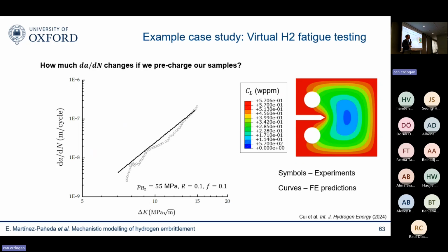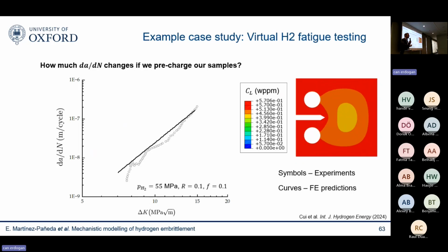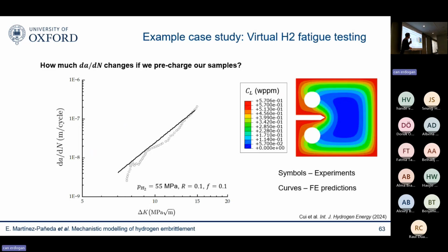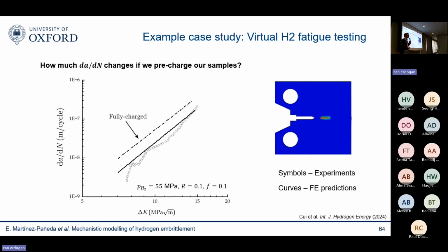So we just expose our compact tension sample to hydrogen. We let the hydrogen redistribute in the model. And then once it's completely uniformly distributed, we run our virtual test experiment. And what we see is that you get an elevation of 2.5 times in the fatigue crack growth rate.